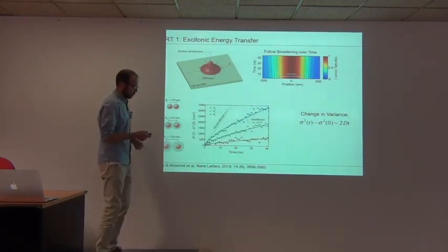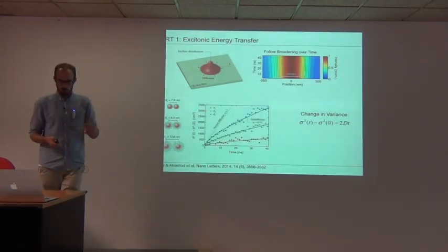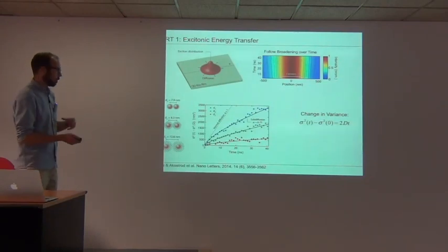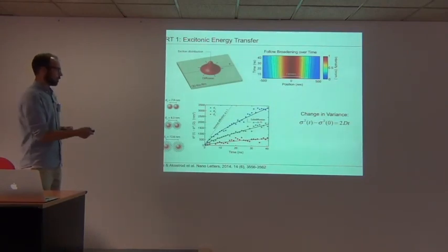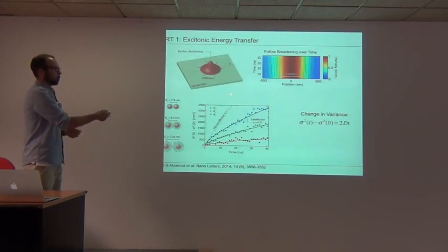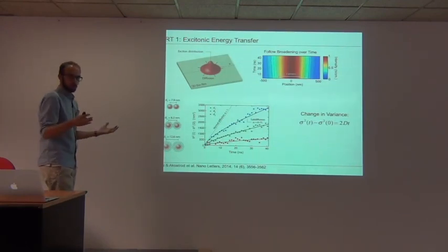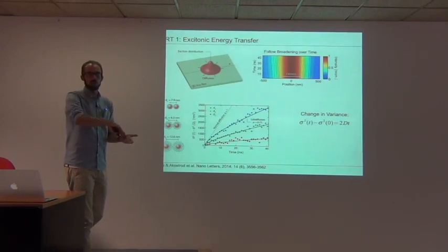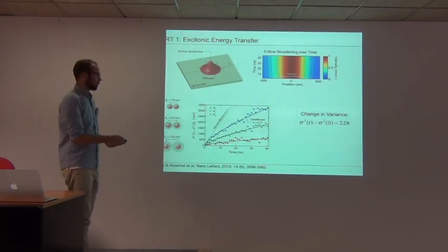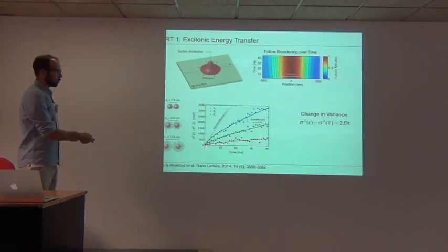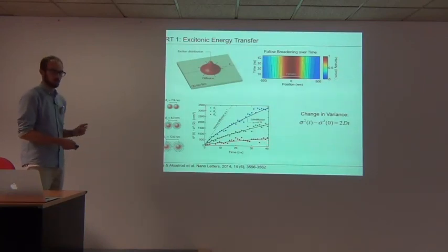And what we observed goes a little bit into the details of how energy transfer is affected by energetic disorder and those kinds of things. What you would expect naively for just a random walk is normal diffusion, so it just diffuses out at a constant rate. Something that we observed, first of all, is that indeed with the increasing distance we see the diffusivity going down, so this is what we expected.